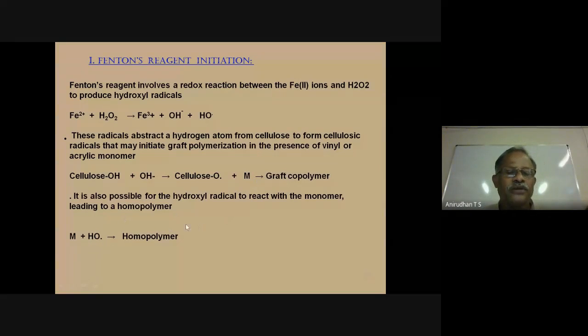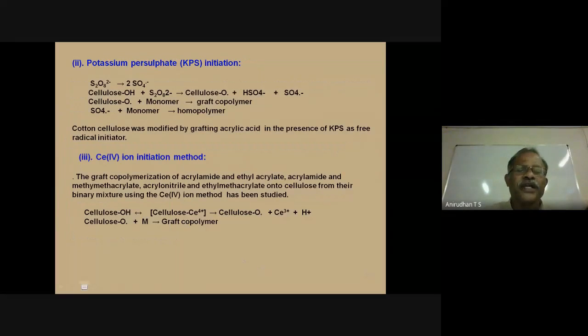Here we also have homopolymer formation, which is of course a disadvantage of these methods, but still we have considered this free radical polymerization. Then another free radical formation is with peroxydisulfate. We break down S2O8 2- into SO4 negative radicals. After formation, these radicals again react with cellulose, abstract one hydrogen atom, and we have a macro radical, which is highly reactive and reacts with the monomer to form graft copolymers.